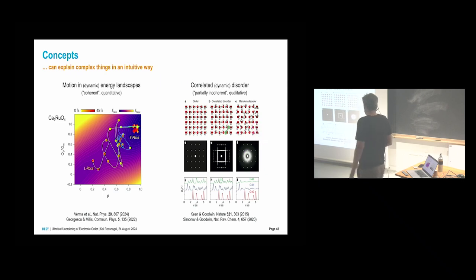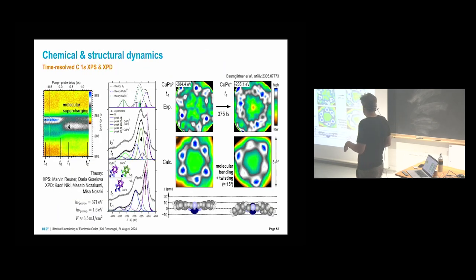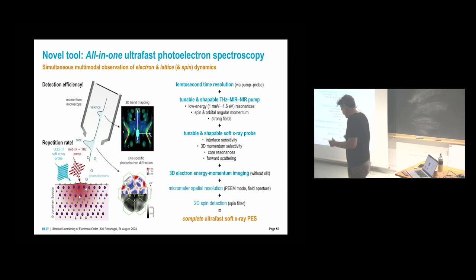Okay, then I would talk about a few more experimental developments, which I really like. But in the end, I want to advertise this. We have looked at electron and lattice dynamics using different techniques: ARPES, time-resolved ARPES, time-resolved X-ray diffraction, ultrafast LEED, and so forth. How about combining this in a single experiment? Here, photoelectron spectroscopy can be a cool tool because there are different modalities of photoelectron diffraction. One we all know is ARPES for band structure mapping. But if you look at the core levels, you can also do photoelectron diffraction and thereby get information on the lattice and its dynamics. And we want to combine this in a single instrument.